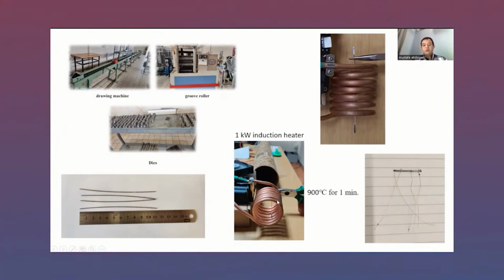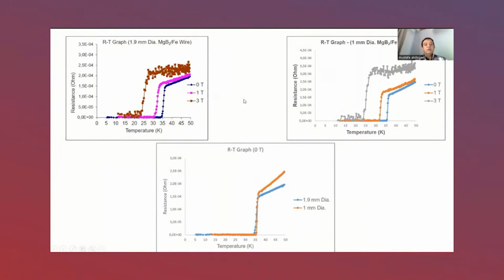Actually, we tried different temperatures, and finally we got the result from 900 Celsius for 1 minute. And we have applied the four-probe technique on our samples, taken from the center of these induction heated wires. Here are the results of our samples. Left one is for 1.9 millimeter diameter and right one is for 1 millimeter diameter. You are seeing the resistance temperature behavior of our samples.